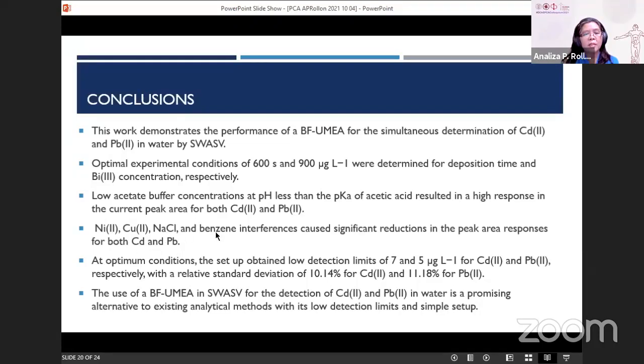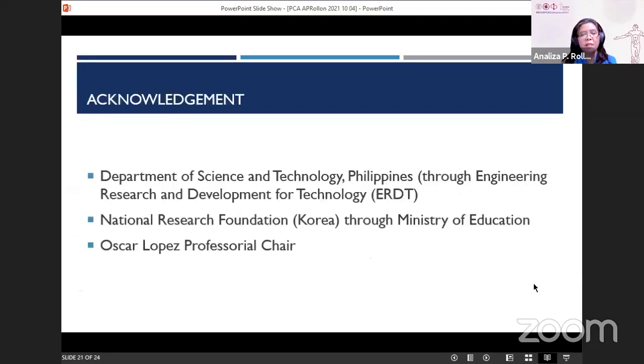These ions interfered with the peak area responses for both cadmium and lead. And at the optimum conditions, the limits of detection were already mentioned a while ago, with a relative standard deviation of about 10 or 12% for cadmium and lead. So the use of the bismuth film ultramicroelectrode array in SWASV for the detection of cadmium and lead in water is a promising alternative to existing analytical methods, with low detection limits and simple setup.